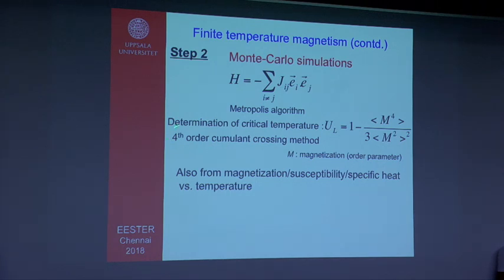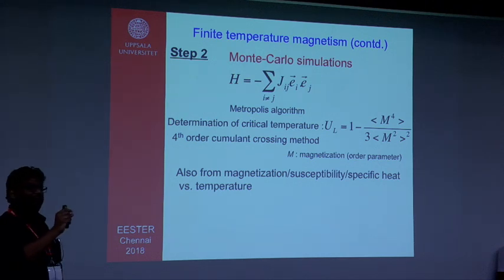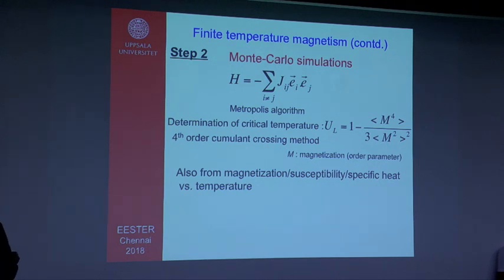One typical way of finding the critical temperature, the temperature at which a system might go from a ferromagnetic phase to a paramagnetic phase, is by calculating the fourth order cumulant crossing. This is a standard method described in statistical mechanics. Also, from the magnetization versus temperature, or susceptibility or specific heat, if you plot versus temperature, you can find out at which temperature the magnetic transition is happening.